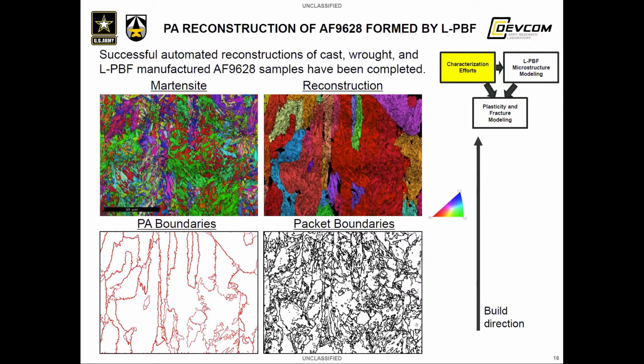Since the martensite transformation is caused by rapid cooling, it's not yet directly known if this form of epitaxial growth happens due to the persistence of austenite grains from layer to layer, or if reheating as the laser passes over previously centered regions causes the reverse transformation of martensite back into the same austenite grain orientations as before, which would provide the orientation preference for the newly solidified material.